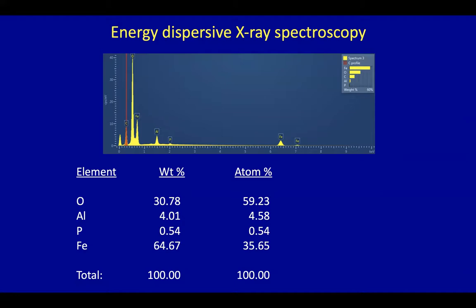But I was familiar with the fact that in hematite, the most common substituting impurity is aluminum for iron. And so we said, well, what if this is just getting incorporated into the hematite structure, and these are indeed just hematite nanocrystals? If we do that, we can generate a formula that's not quite Fe2O3. It's what you see right here, with aluminum and phosphorus substituting for the iron.